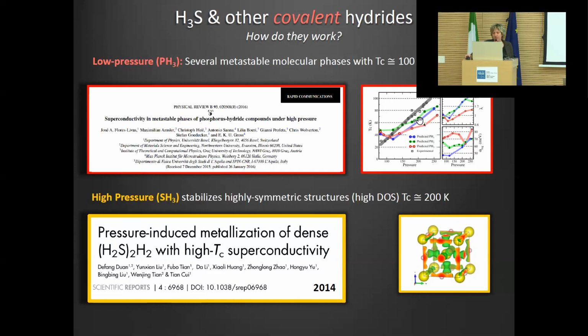So below phosphine, I mean, it's exciting for this reason, but you see the highest Tc is of the order of 100 K. And below phosphine, we have the star, so the first really high temperature hydride. And this is SH3. And what I'm reporting here is not the experimental discovery, which came at the end of 2014, but the first paper which actually predicted what the RMS group observed, so that actually if one mixed in a diamond anvil cell H2S, so hydrogen sulfide with hydrogen, with a high enough pressure, one would realize something which would be crazy to see at ambient pressure, and which is SH3.